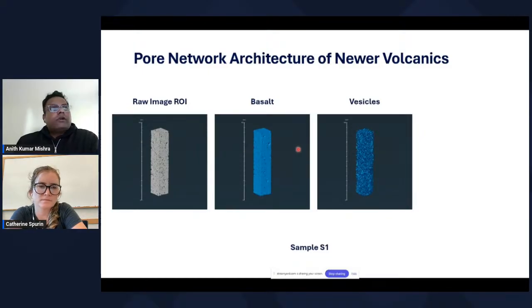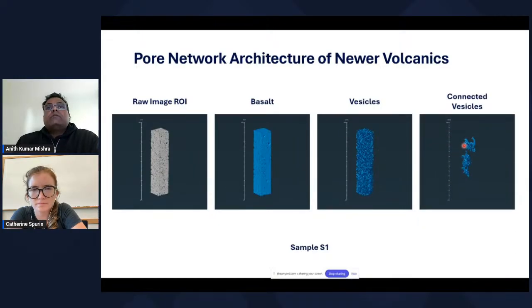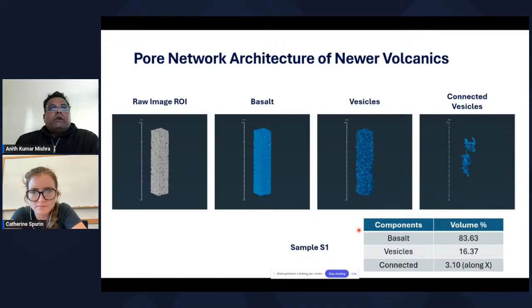Since we do not have any secondary mineralization in these basalts, volumetric rendering only comes up with the basalt and the vesicle network. And here we try to see the connectivity. We found some connectivity, and we also quantified the volumetric components. In this particular sample, the basalt is 83%, the vesicles constitute 16%, and the vesicle connectivity is 3%, but the connectivity is only found along X. No connectivity was found along Z, which is the vertical dimension here.